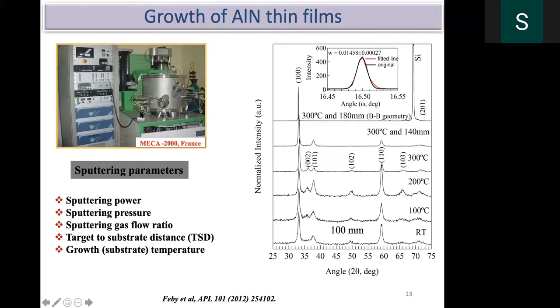This is a simple magnetron sputtering technique, semi-automatic. It's not completely automatic. You can control the sputtering power, and you can control the pressure inside the system, and then the gas flow, that is, whether you want to have argon or argon to nitrogen, which ratio, and the target to substrate distance, which is a very important parameter, and the temperature of the substrate. All these things play a very important role.